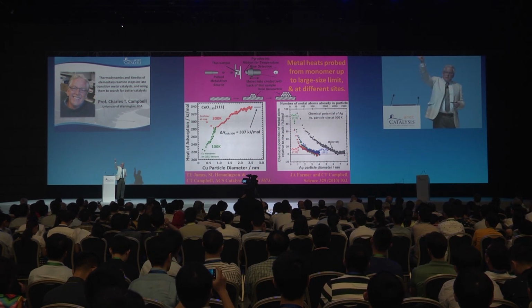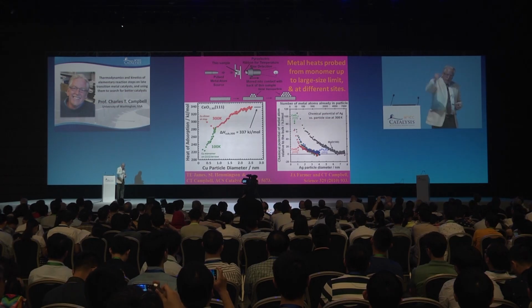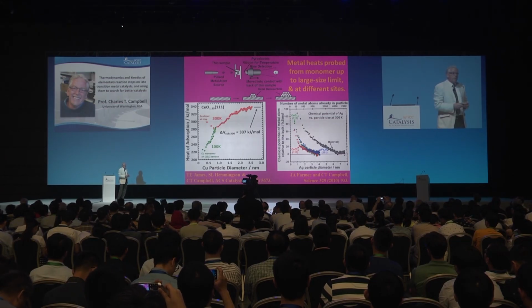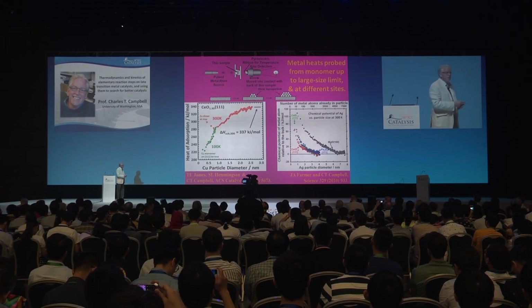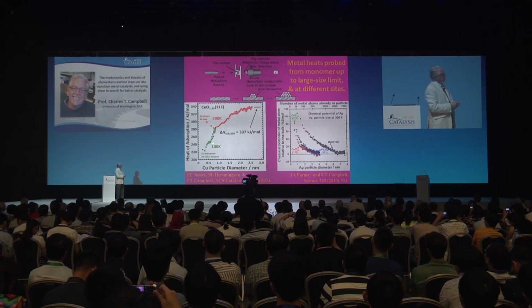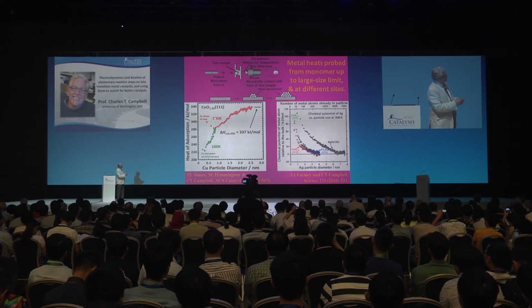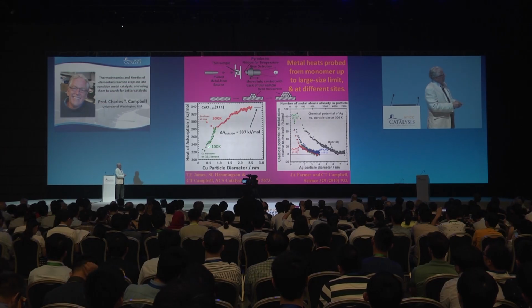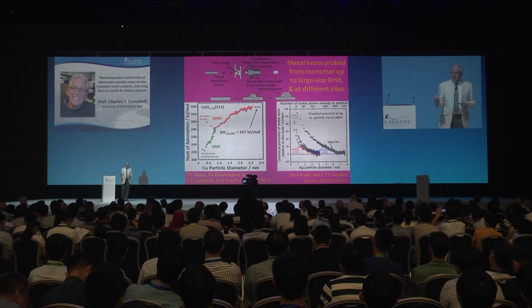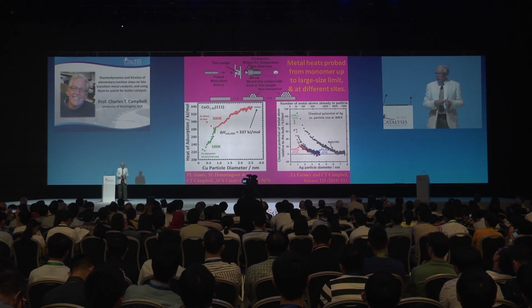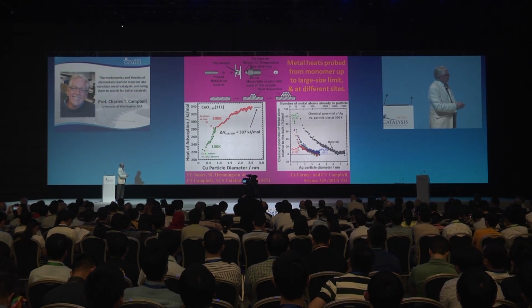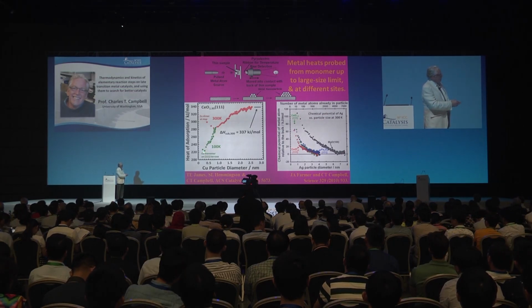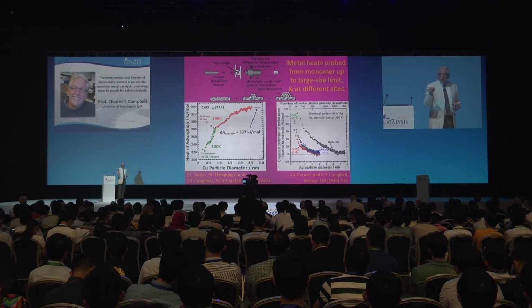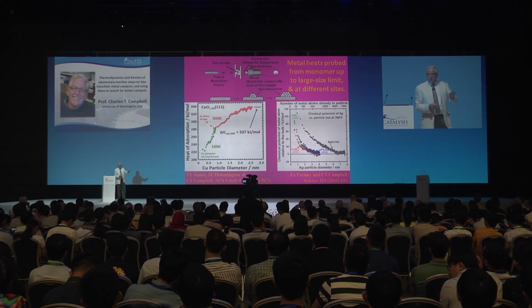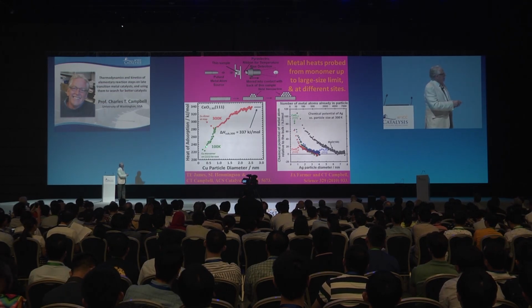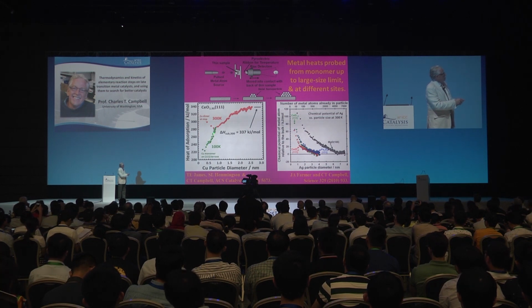So it's the difference in energy between a gas phase copper atom and a copper atom in the nanoparticle at the particular particle size that's the average particle size at that coverage. And so these are two experiments, one at room temperature and one at 100 Kelvin, where the copper atoms are much less mobile on the surface. And at 100 Kelvin, we can actually get copper monomers. The first 2 data points are for copper monomers on terraces because they're so immobile, and then you start nucleating particles and they grow bigger.